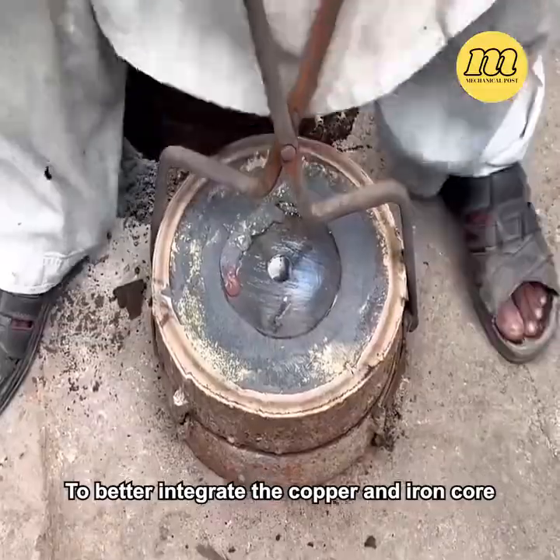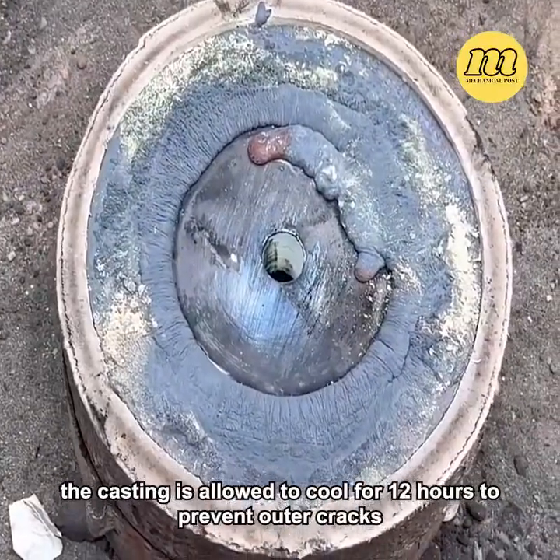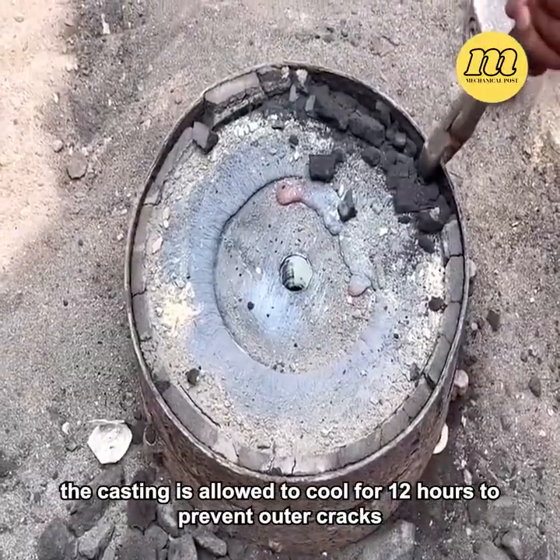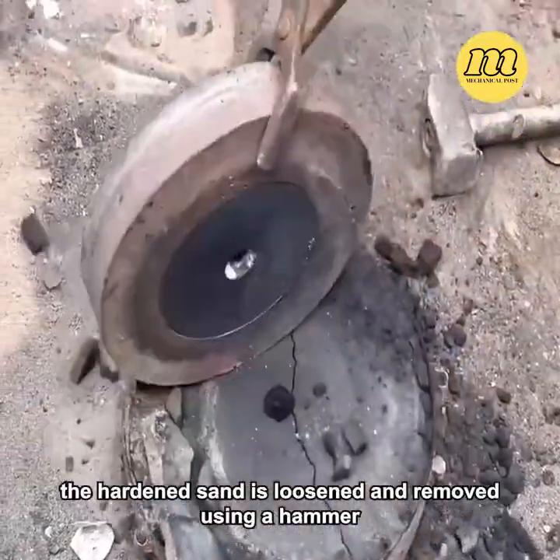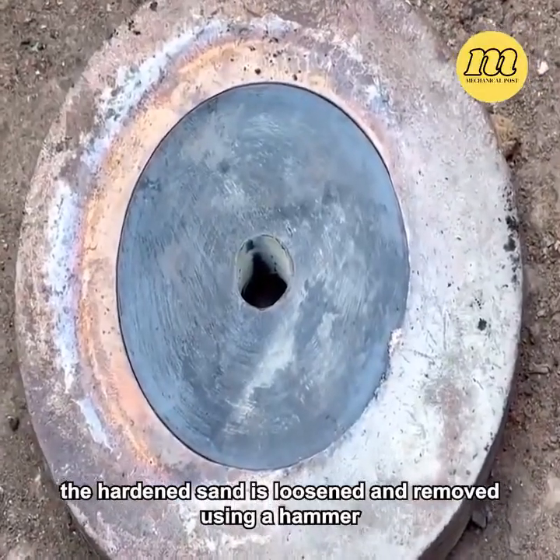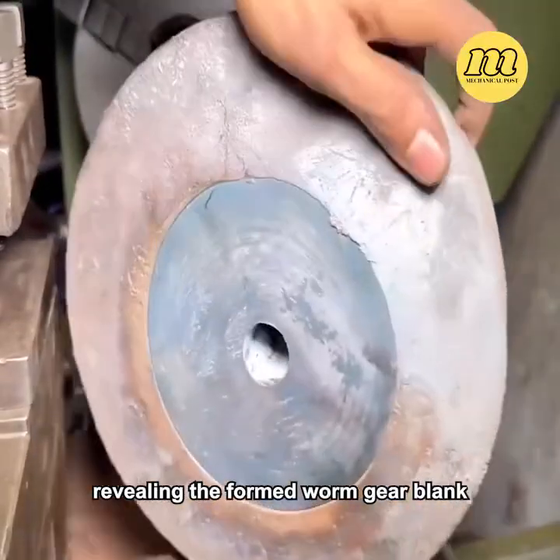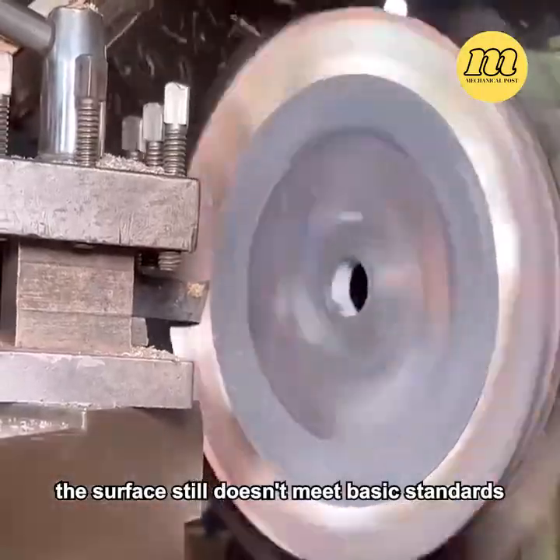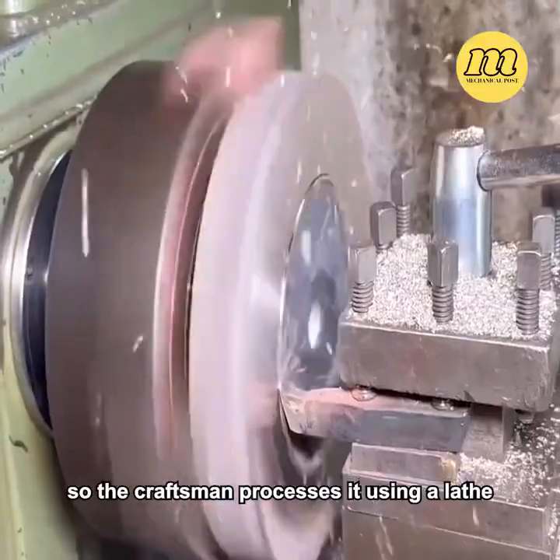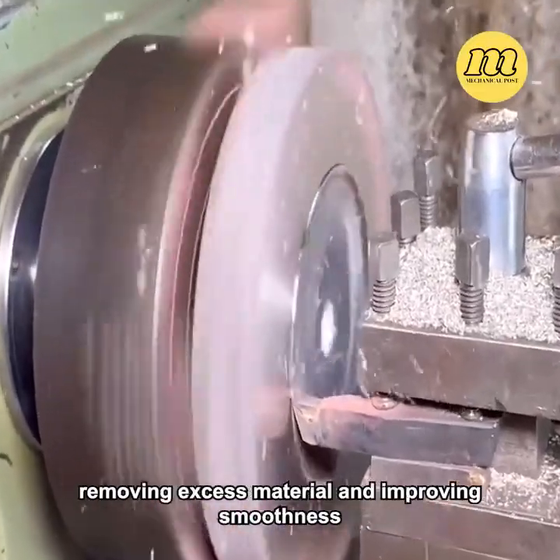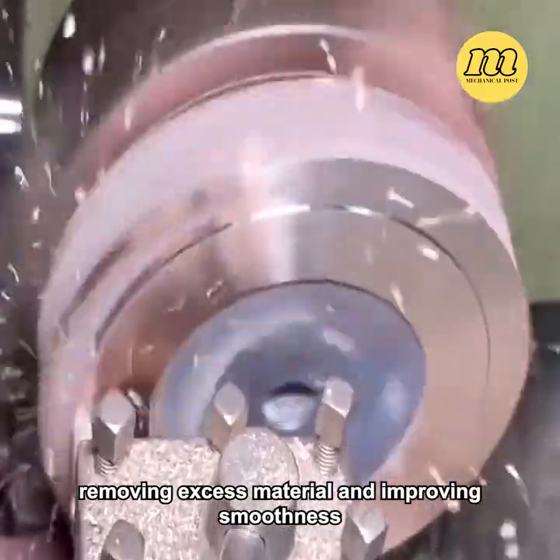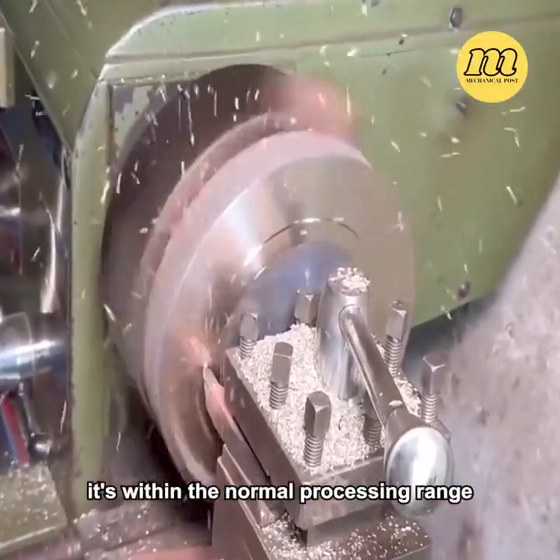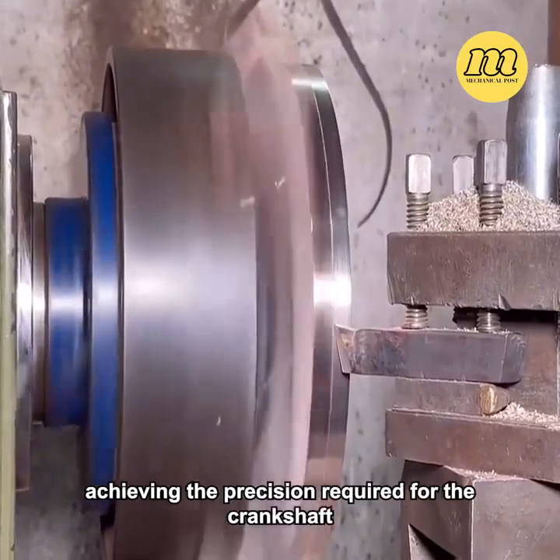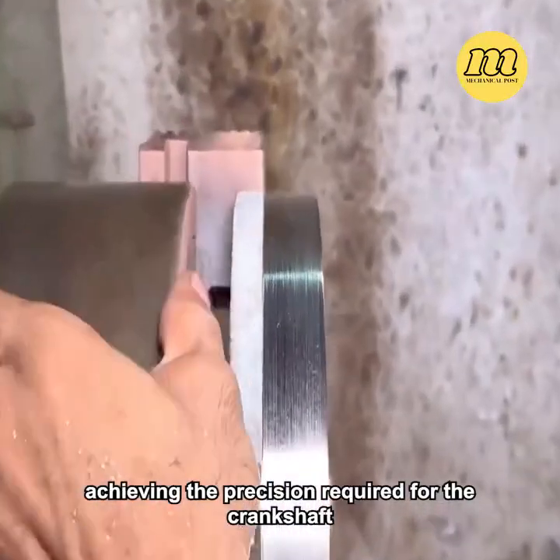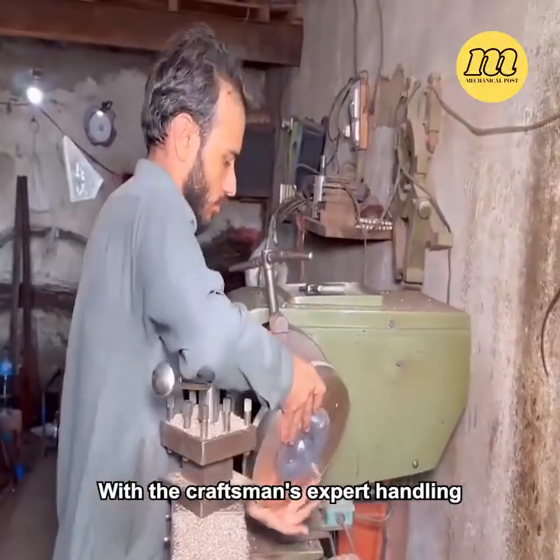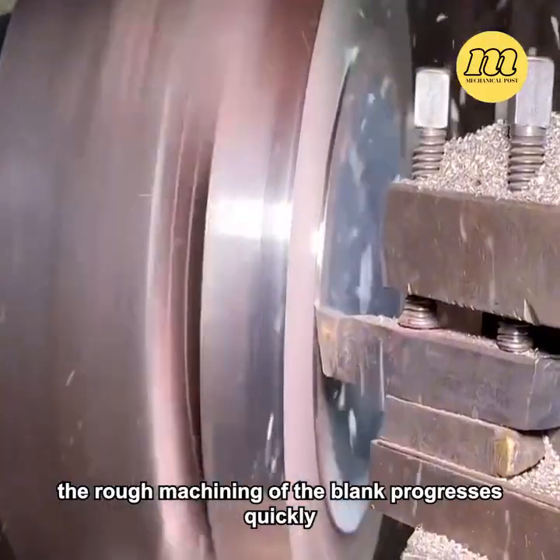Once all the molten copper is poured in, it levels with the iron core surface. To better integrate the copper and iron core, the casting is allowed to cool for 12 hours to prevent outer cracks. Then, the hardened sand is loosened and removed using a hammer, revealing the formed worm gear blank. However, the surface still doesn't meet basic standards, so the craftsman processes it using a lathe, removing excess material and improving smoothness.